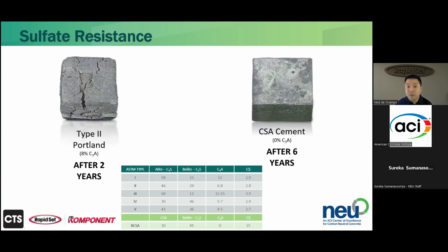In CSA cement, because there is no C3A present, it simply has nothing for sulfate to attack. After 6 years of being exposed to a sulfate environment, the CSA cement block shows very little, if any, deterioration as a result of delayed ettringite formation.